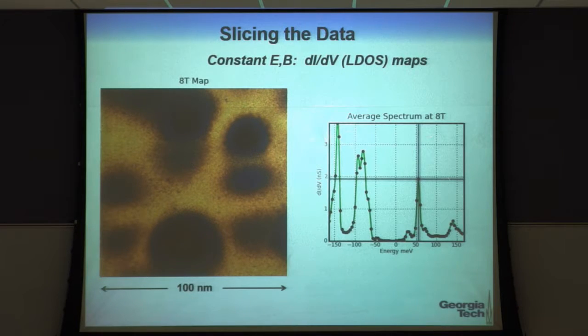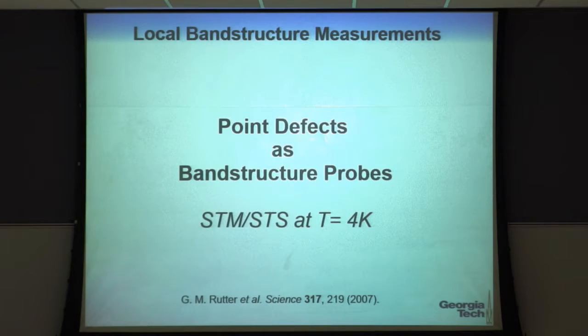So here I show the average spectrum averaged over all positions on this surface. We have taken 100 by 100 spectra on this surface, so at every one of these XY points there's a spectrum like this, okay? And we take one energy and we display it as a map, like so. And if you're on this peak, it happens to look like so, where the dark is low density of states and light is high density of states.